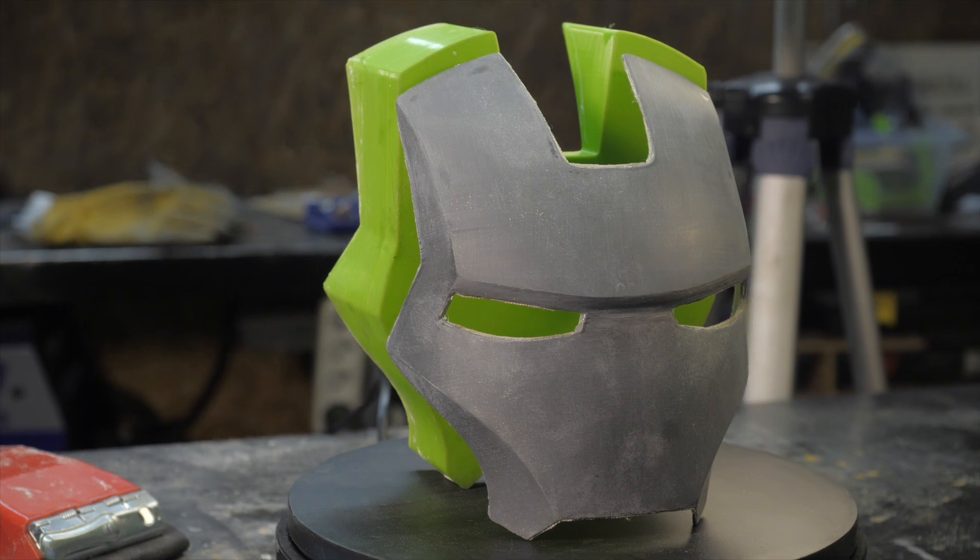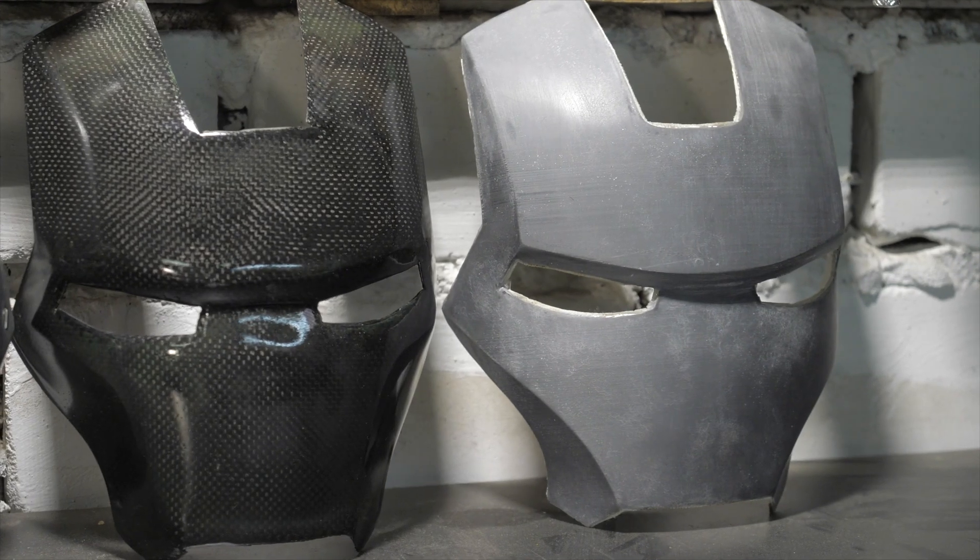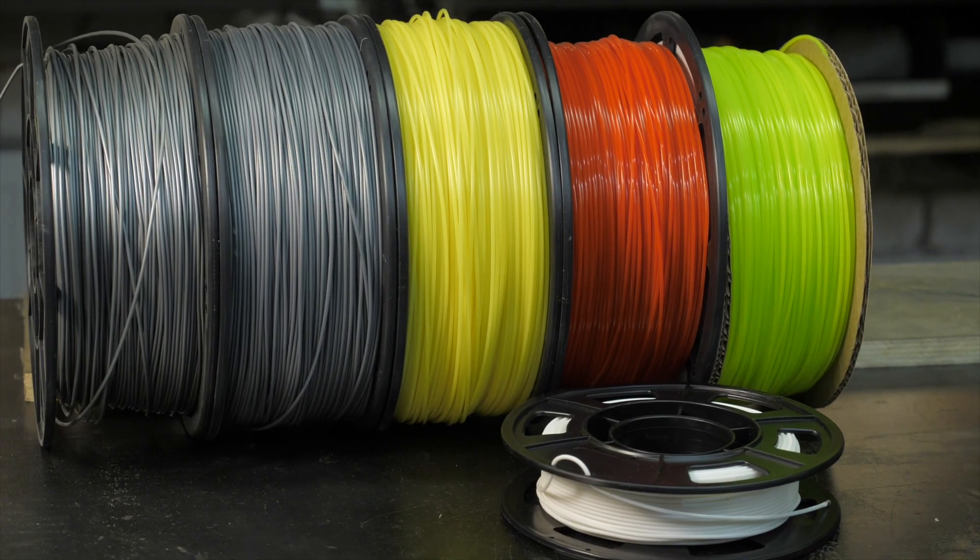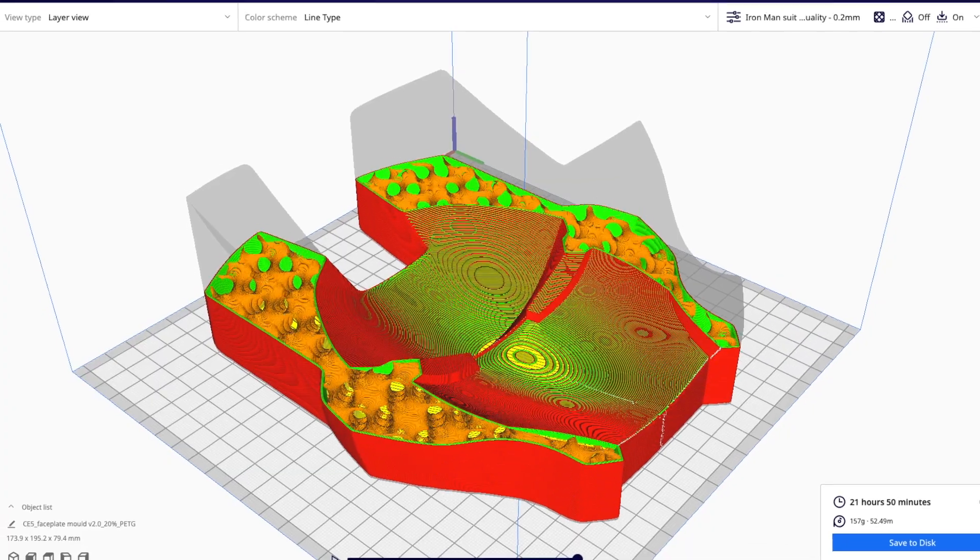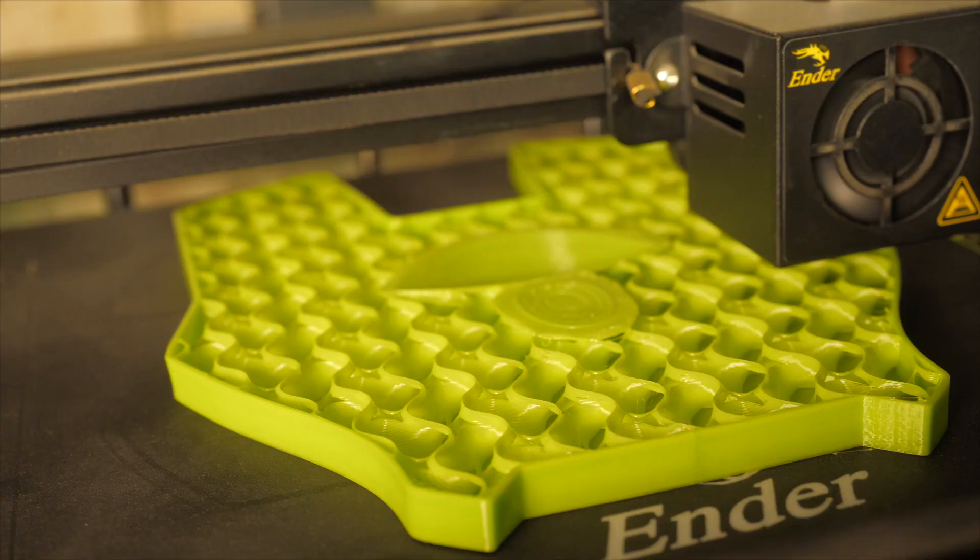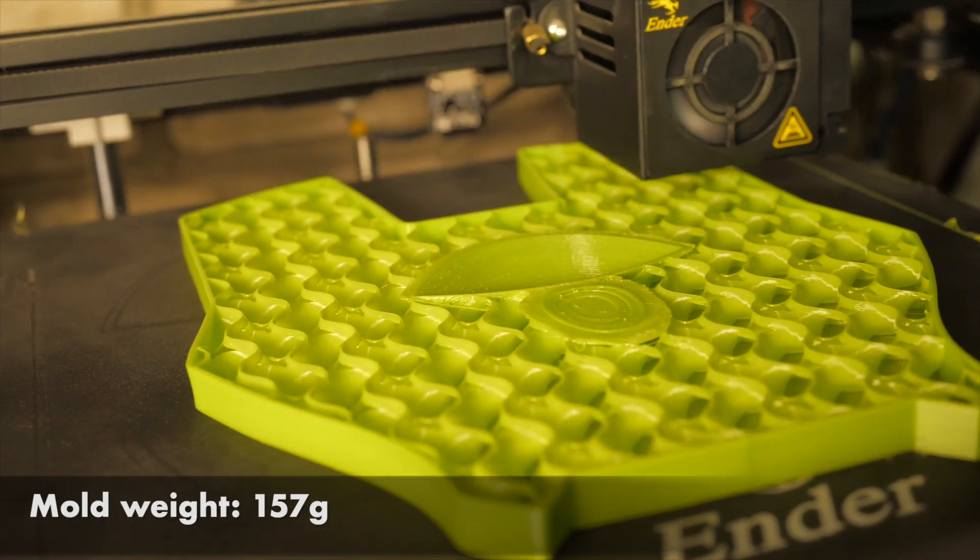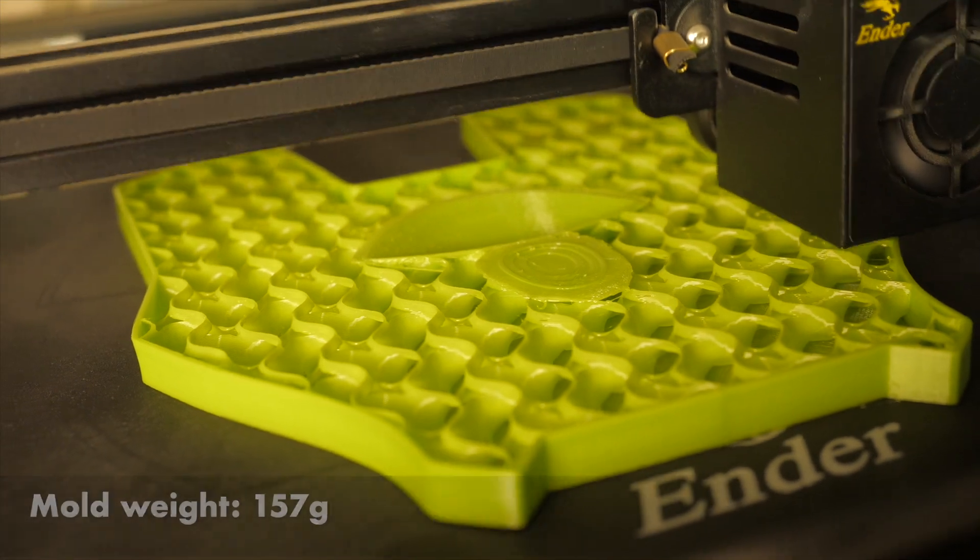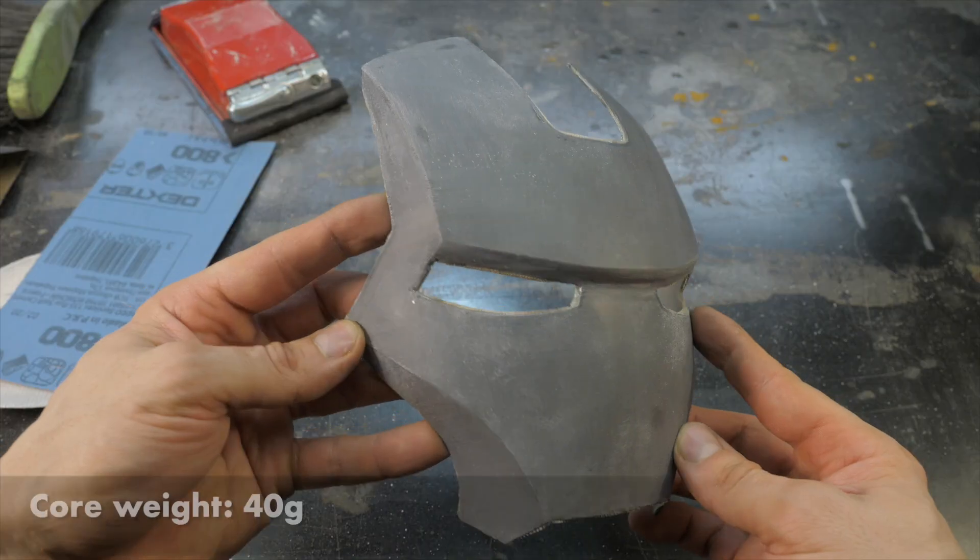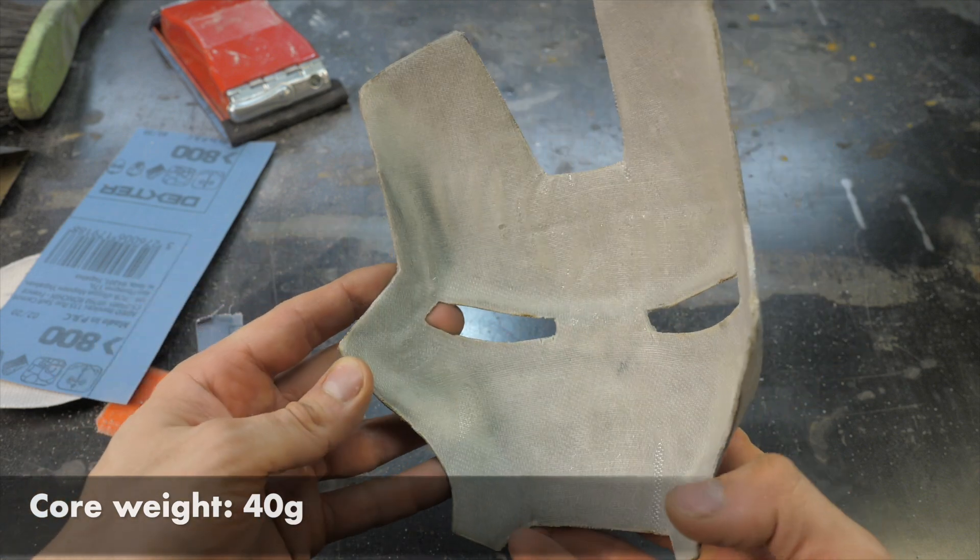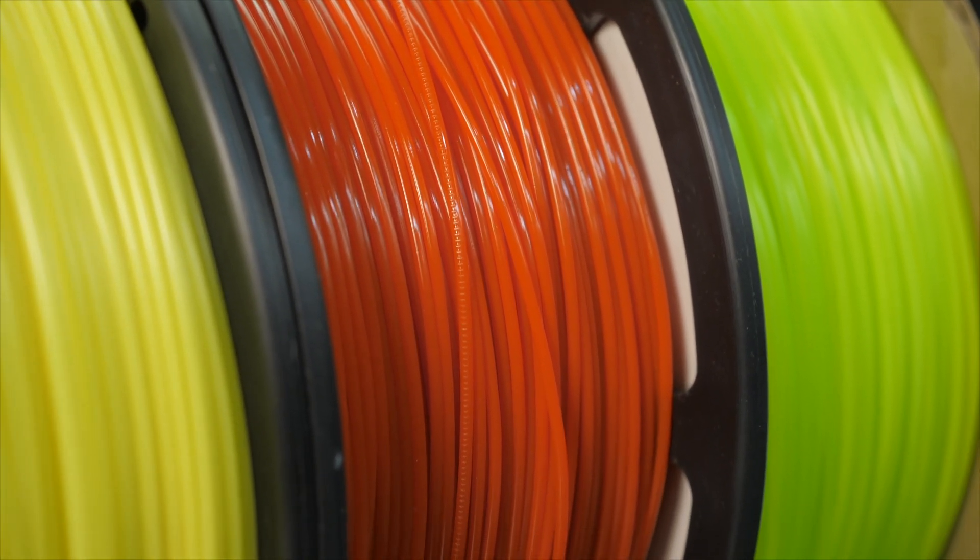Summing up, what advantages technology gives us production of composite parts without a mold for laminating? The first is plastic savings. Even with optimal print settings, complete absence of support parts and 5% fill factor, it takes 3.5 times more plastic to print the mold, which after production must be thrown away, as opposite to the matrix, which becomes the part of the final detail. This way, we don't throw away plastic at all.